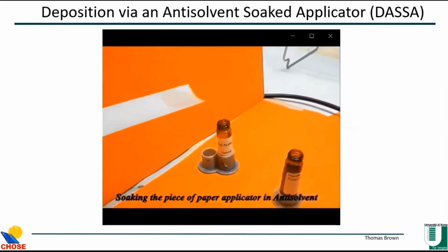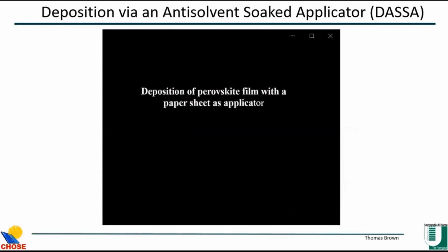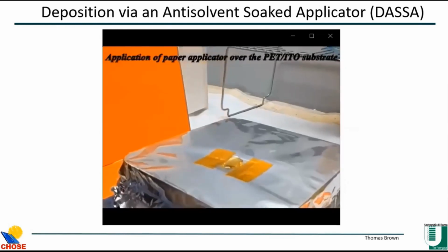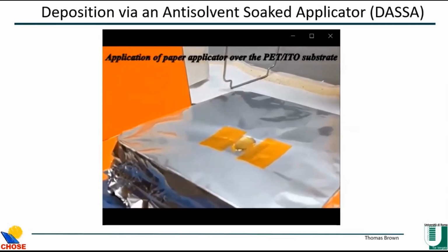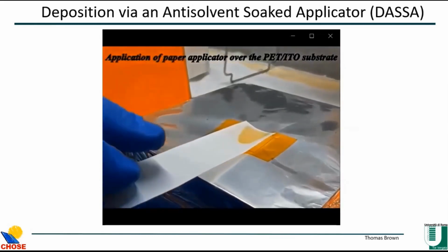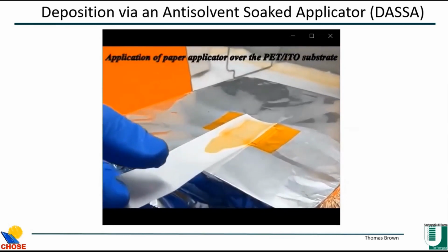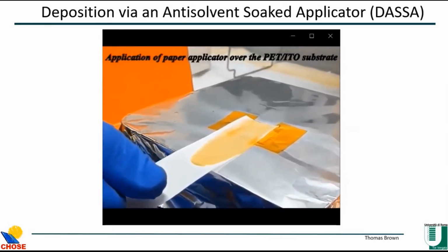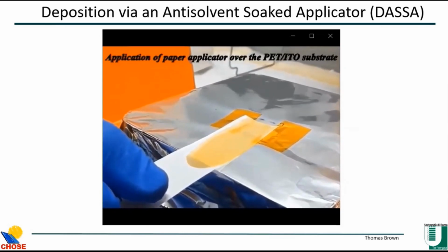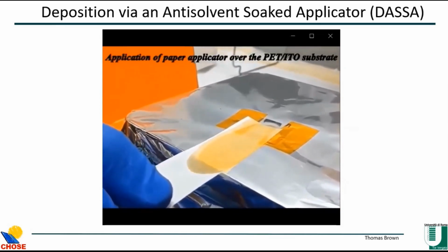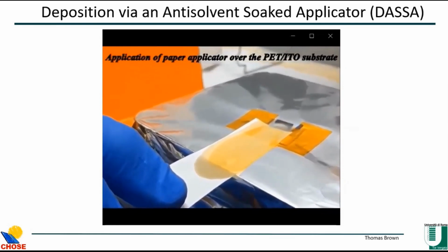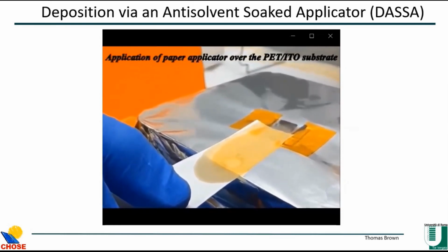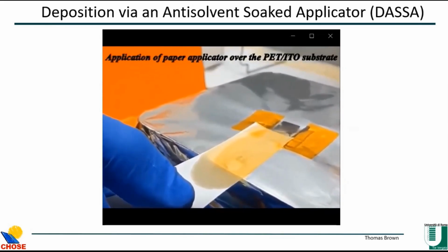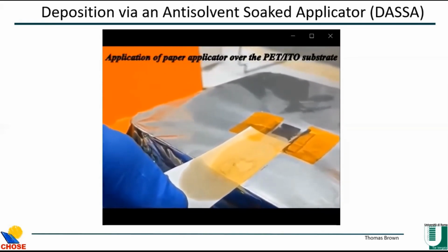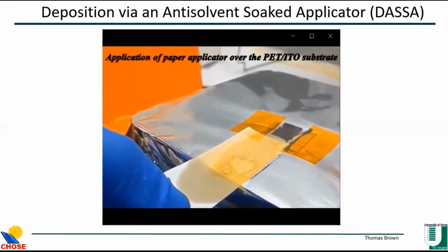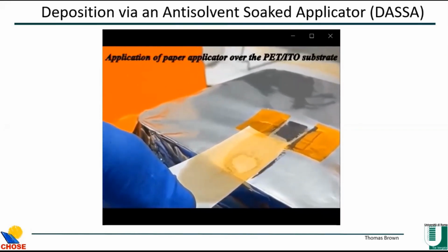So we soak the piece of paper in anti-solvent, ethyl acetate in this case, apply the precursor solution, and this is soaked in anti-solvent. You draw it from one end to another. The hot plate is in this case at 125 degrees. So it helps the conversion of the perovskite, and it's compatible with a plastic substrate. And you see here at the trailing end, it's converting into perovskite. And the drawing speed is about 0.1 centimeter per second.